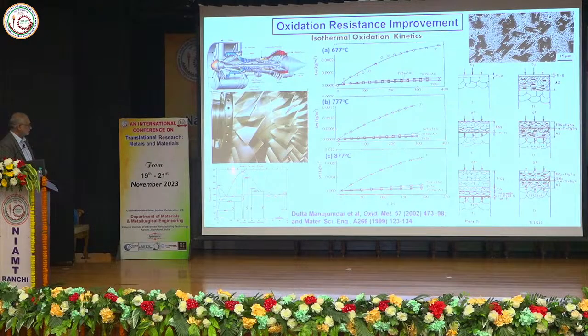So what she did was to pick up a composition in the hypoeutectic zone, but because of faster cooling, these liquidus curves actually plunge, and as a result she ended up getting a hypereutectic microstructure in a hypoeutectic composition because of non-equilibrium cooling. What is the advantage? The advantage is nearly 85% of this microstructure is covered by a phase which has a very high melting temperature, very low coefficient of thermal expansion, and most importantly is much more stable and oxidation resistant than many metals, and even many oxides.